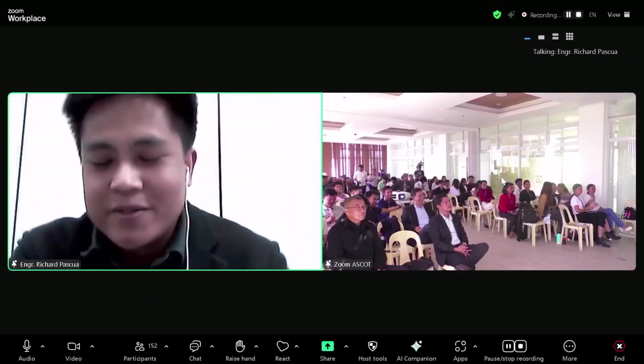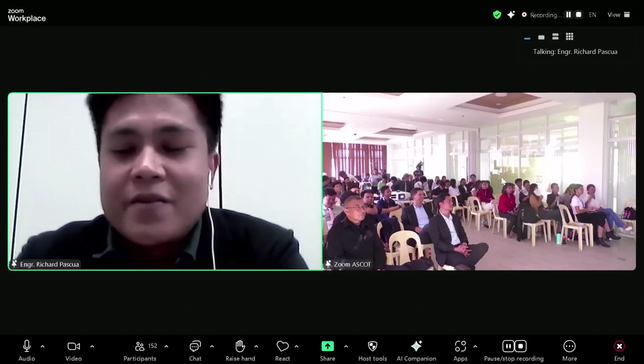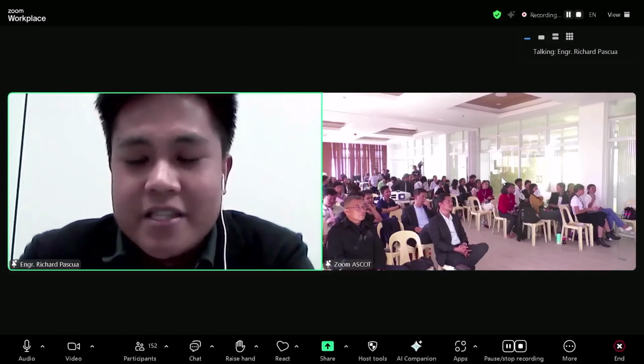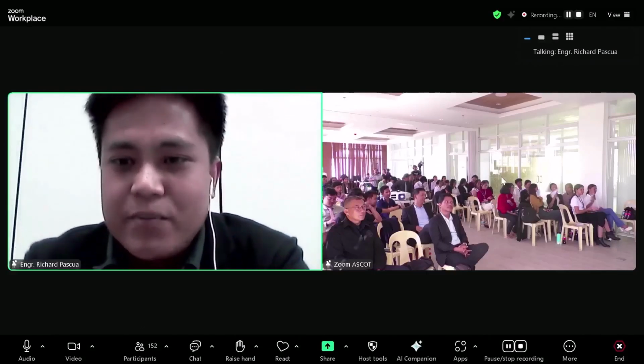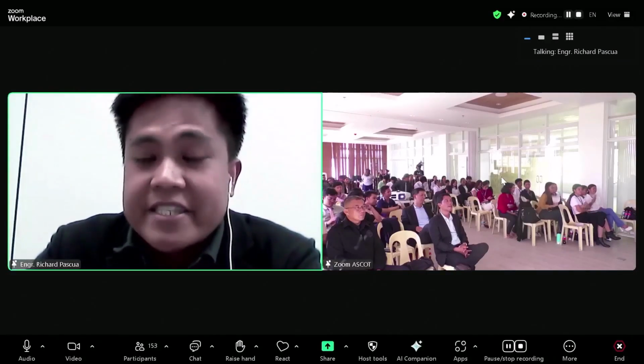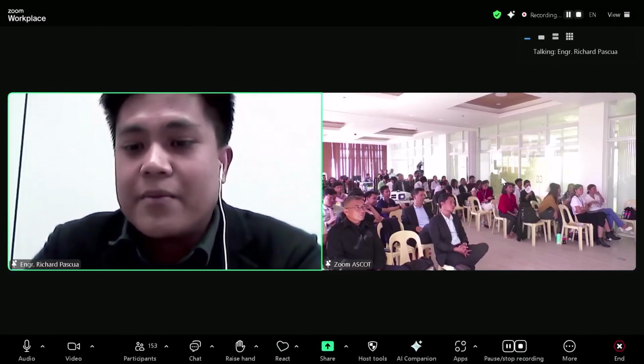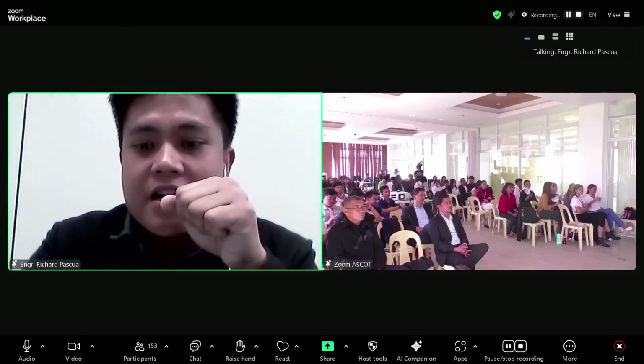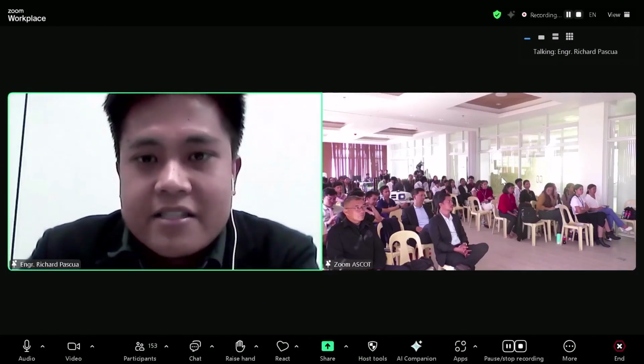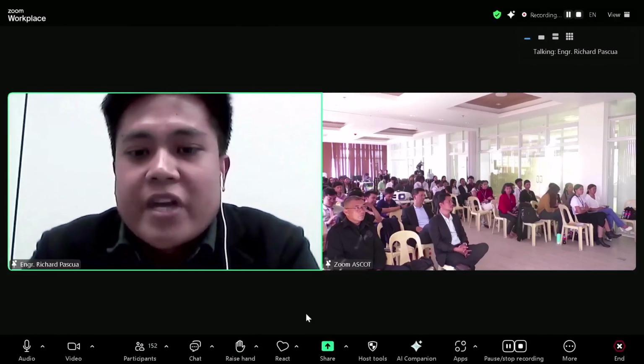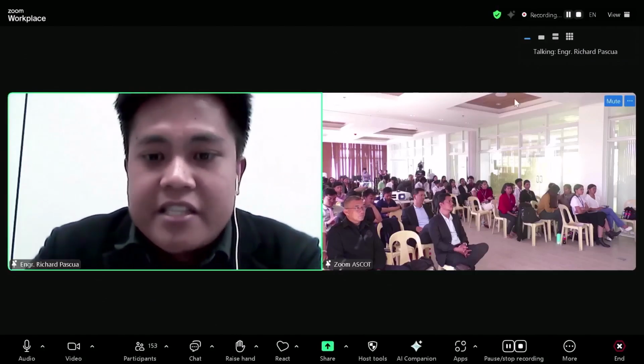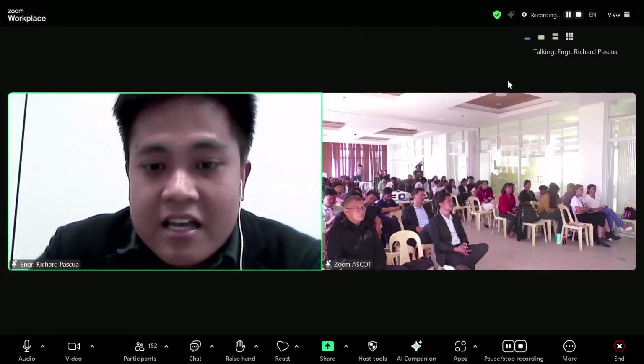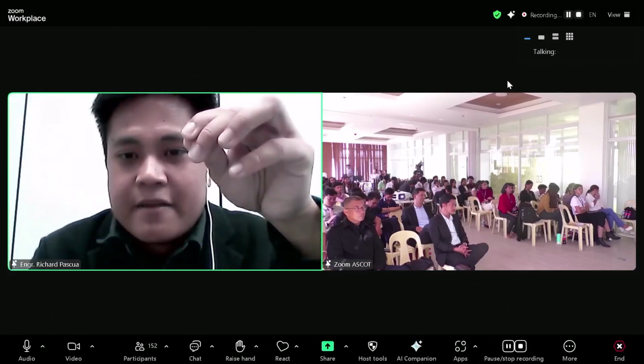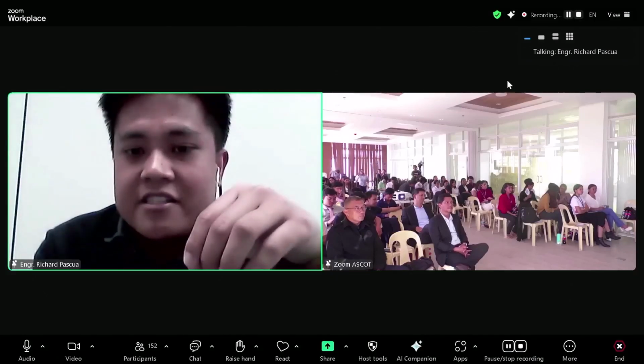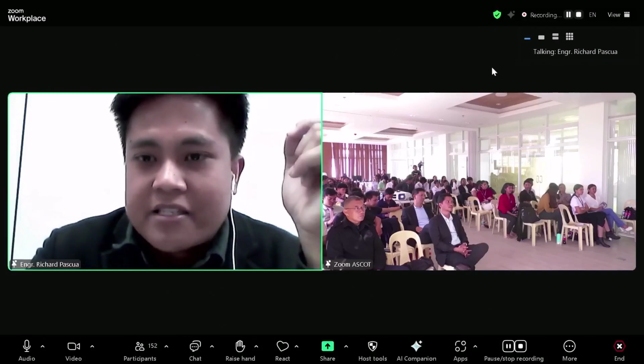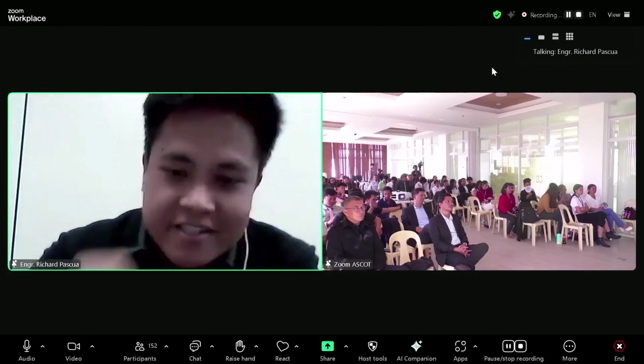Okay, so in situ, actually there are two types of methods, the ex situ and in situ method. In the in situ method, we evaluate the material while exposing it to an external hydrogen environment, meaning the hydrogen comes from the external to the internal of the specimen. While the ex situ uses electrochemical hydrogen charging, which is they diffuse the hydrogen into the material first before conducting the test. Or the internal, it's an internal hydrogen environment, and the in situ is under external hydrogen environment. Thank you, sir.